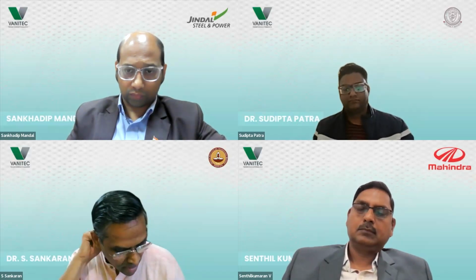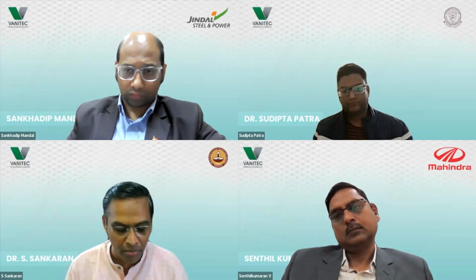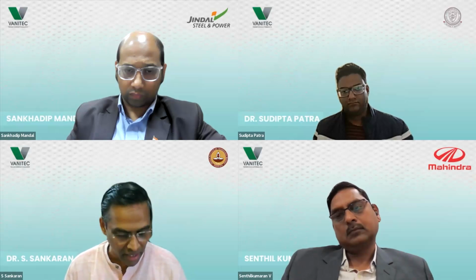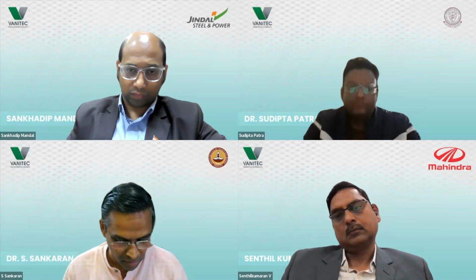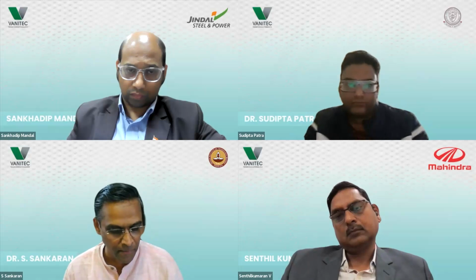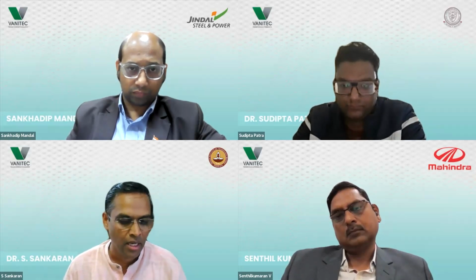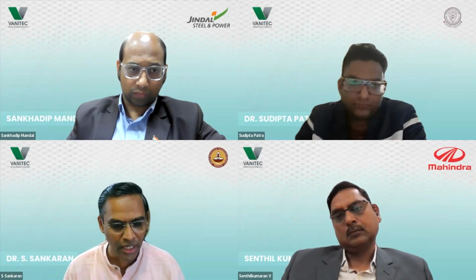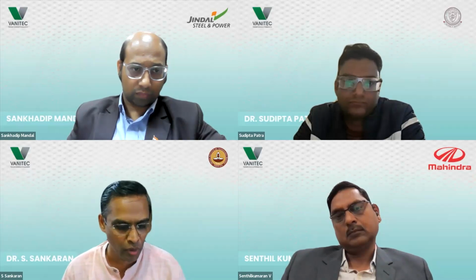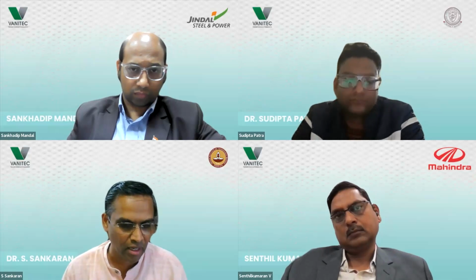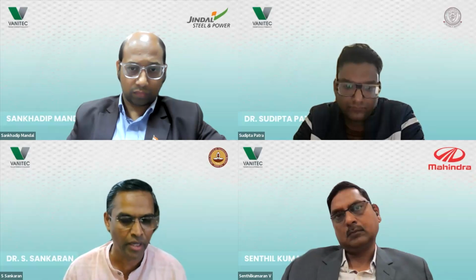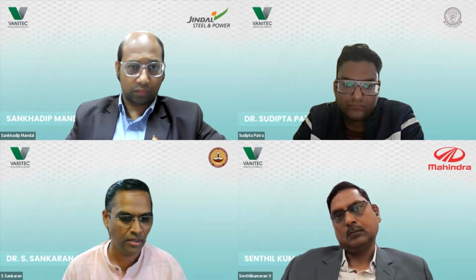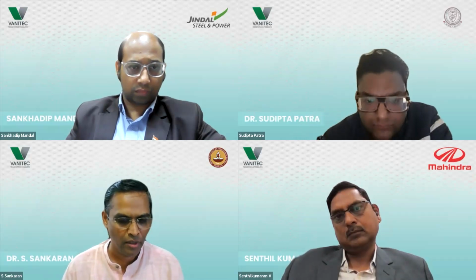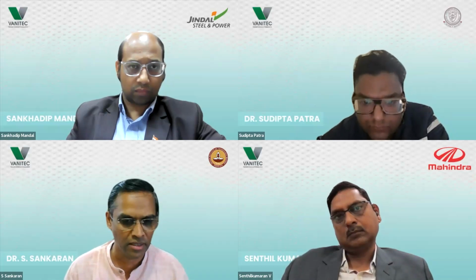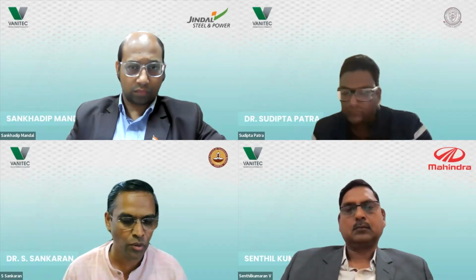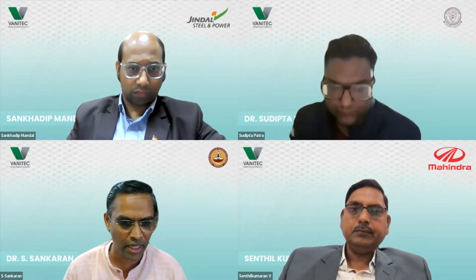And later, when I came to Madras, we again used these vanadium and niobium microalloyed steels to produce ultra fine grain steels. There again we found a challenge, because characterizing these complex precipitates remained a huge challenge. The microstructure is so complex, because we wanted to produce very ultra fine grains in a dual phase microstructure. So you have martensitic and some bainitic phases, which are very complex, and identifying the precipitates forming in these matrices creates a lot more challenges. So again, we tried these replication techniques and then characterized them.